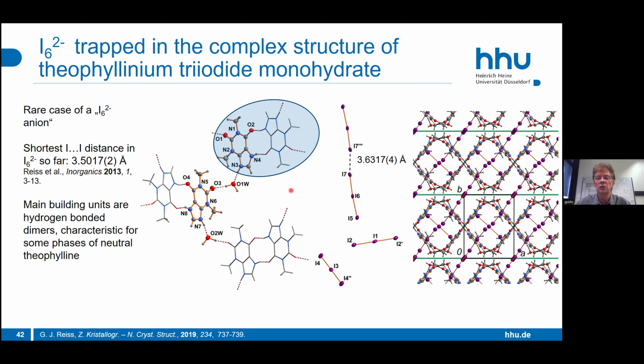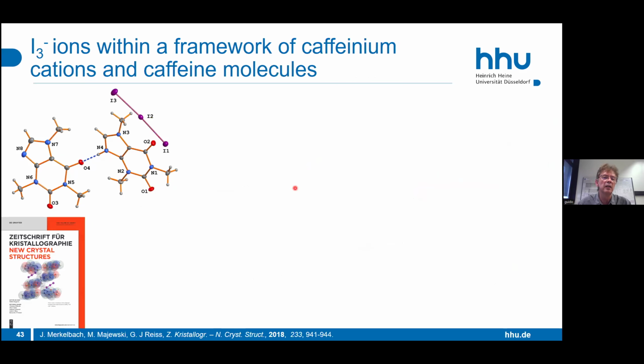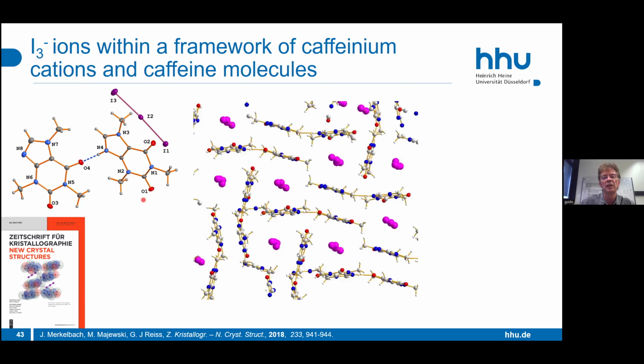the theophyllinium to the caffeinium. If we react caffeine with hydrochloric acid and iodine, the first compound we get is composed of neutral caffeine, a protonated caffeinium, and the counter anion. So this is not so interesting at that point, but if we go to the packing, we see several things. First of all, we see these two molecules connected by a hydrogen bond, and neighboring molecules are parallel to them or perpendicular to them. And as a result, we get again some channels, and in these channels, we still have I3- anions.